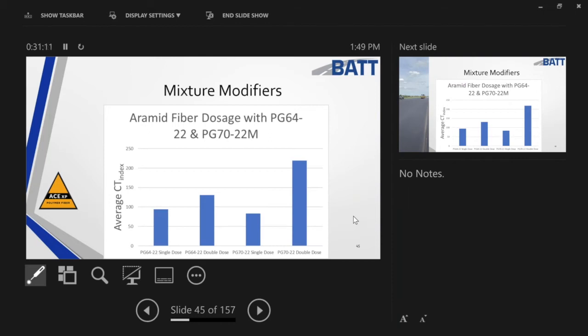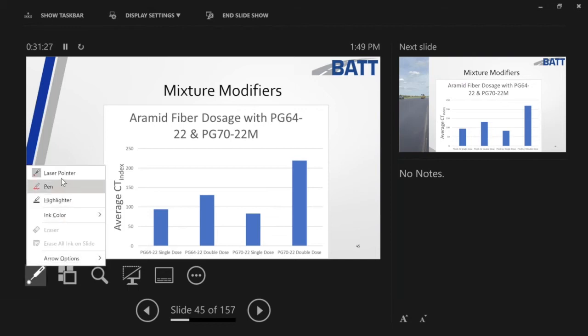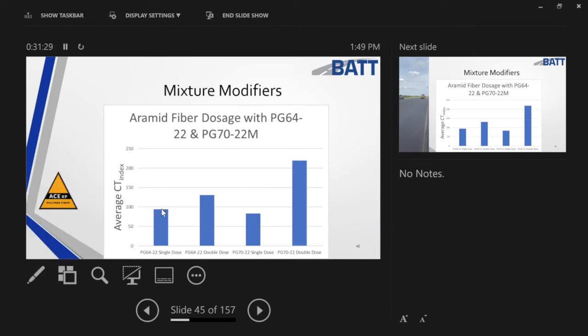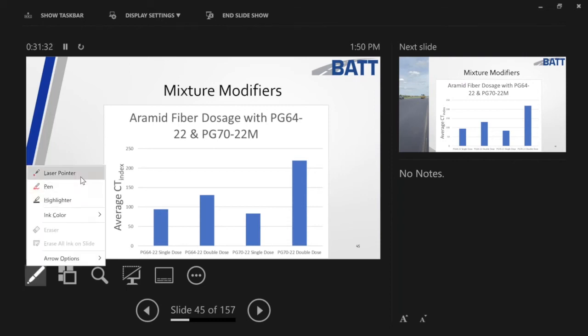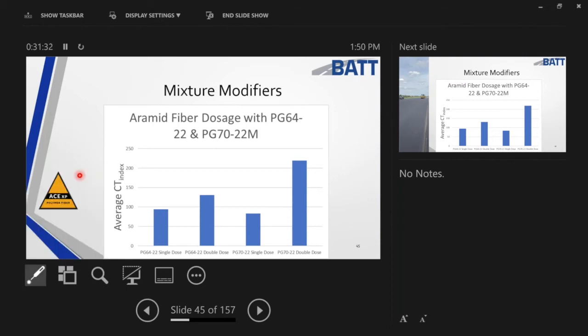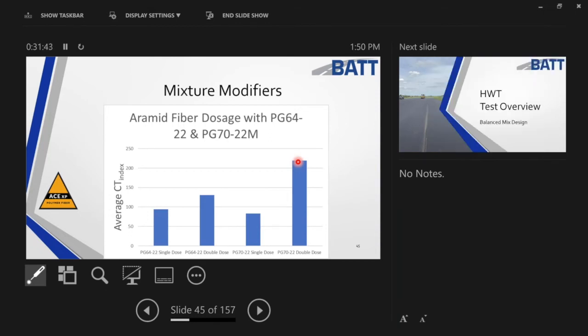So here you see, as I began to put a single dose in and a double dose in a standard 64-22, and then over on the right a 70-22 mixture. As I did this with my 64-22, I went from a 90 up to about a 130 on an Ideal CT. And then I did the same with the 70-22. I was down there in the 80 range, and then adding that double dose took me even higher. Why is that? Because the binder reacts very well with this Aramid fiber, and you need that to hold it in place.